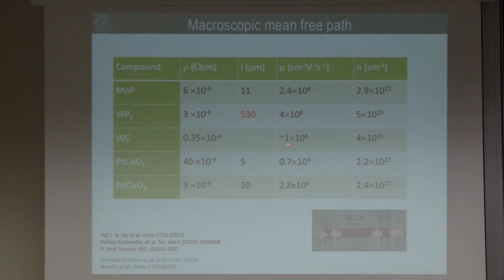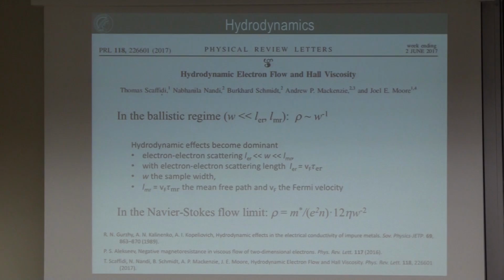So if you calculate the mean free path of the electrons from the mobility, you get a huge mean free path, even much larger than Andy saw for palladium cobalt O2. It's 0.5 millimeter. So you can imagine this is our single crystal, and this is 300 micrometers. So the mean free path of the electrons is huge compared to the single crystal in this material.